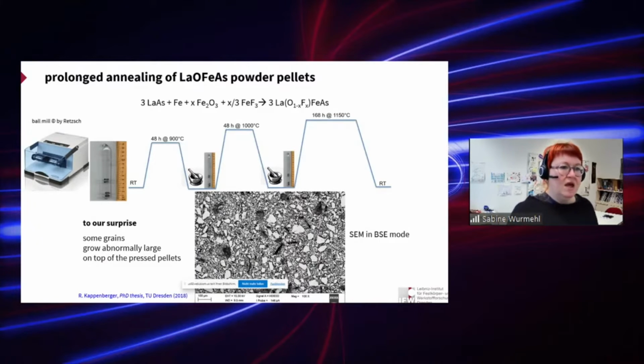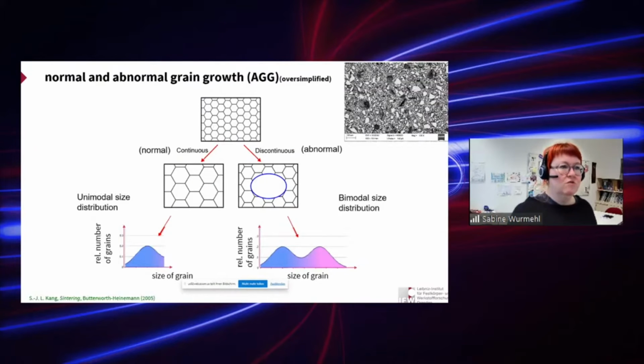If you look here at the microstructure of such a pellet, you see that already some grains are abnormally large at the cost of others, and they are really growing out of these pressed pellets. This was a very important observation from Rea Kappenberger to learn something on how we could grow large single crystals of 1111 compounds, because this abnormal large grain growth may happen in many different systems.